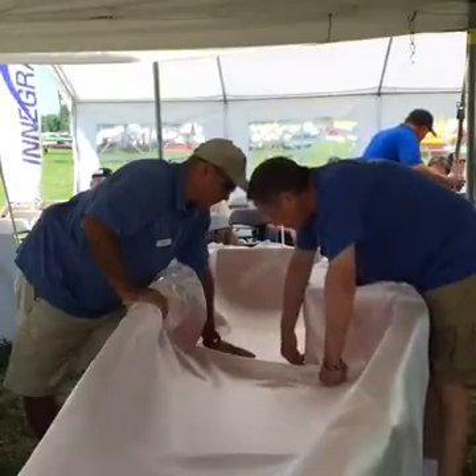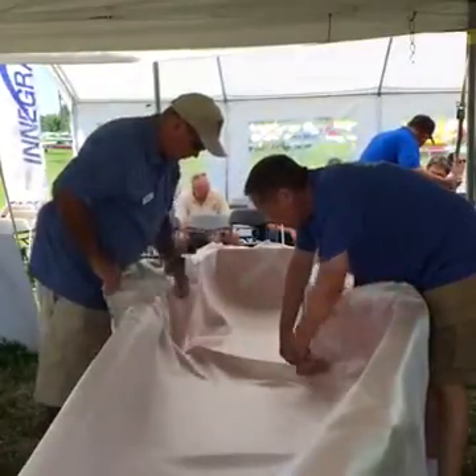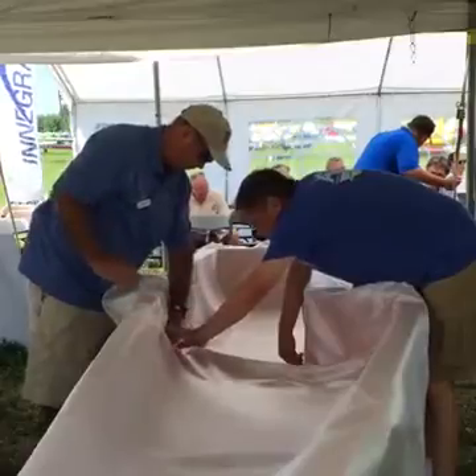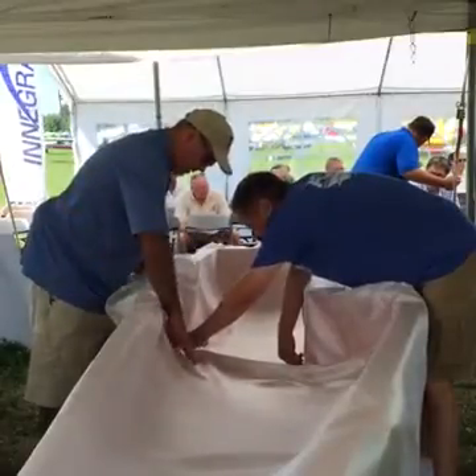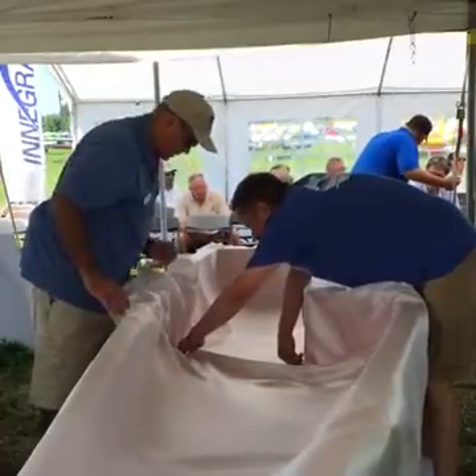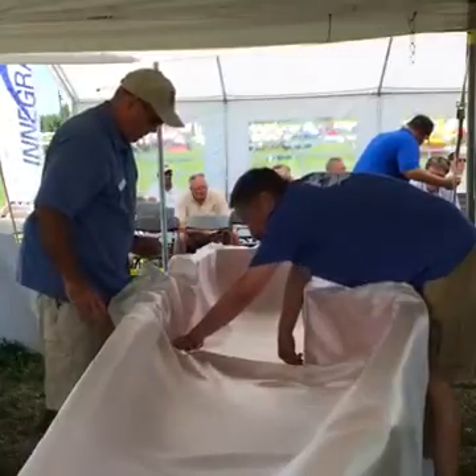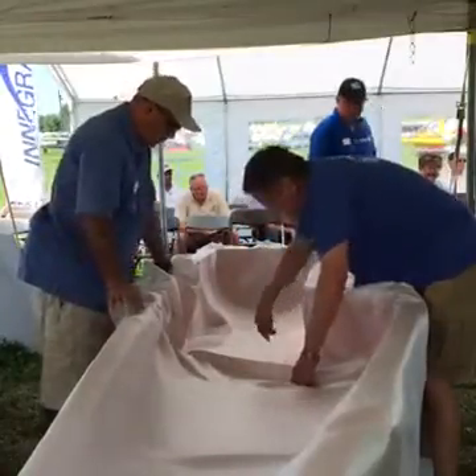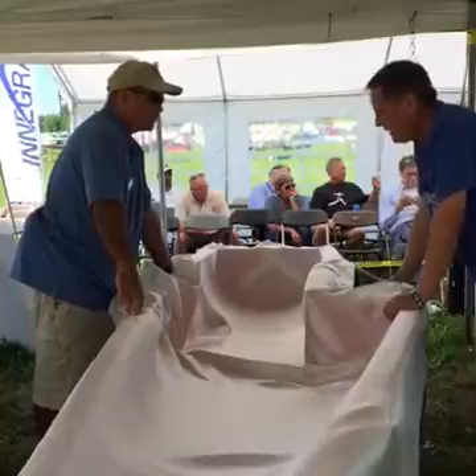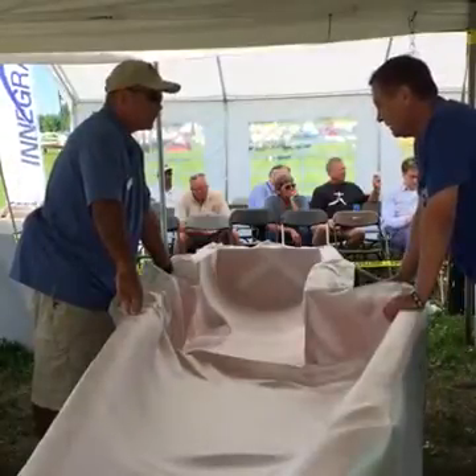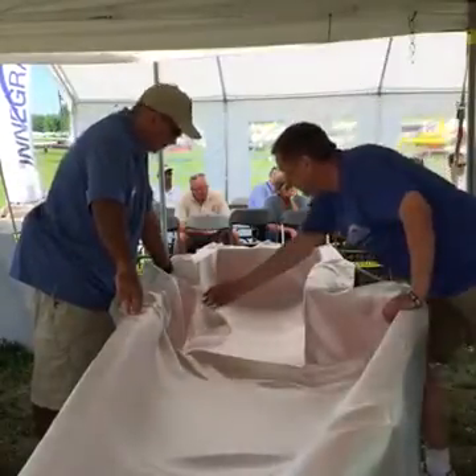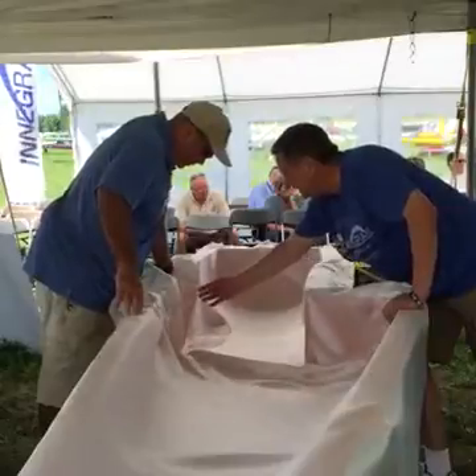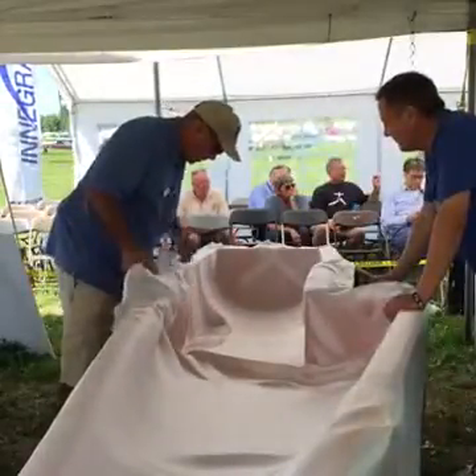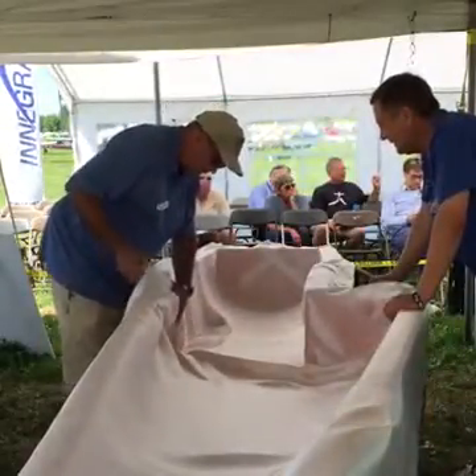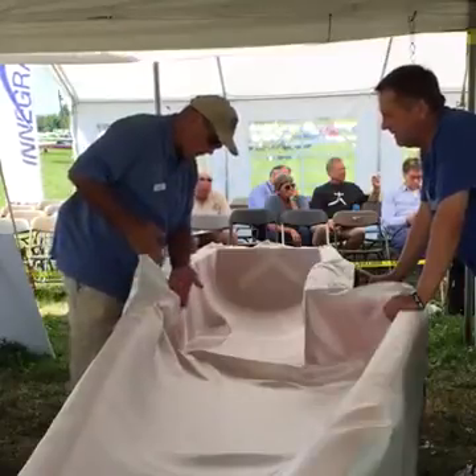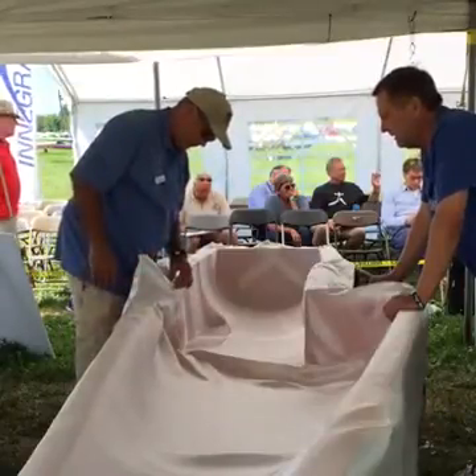So what we have on this part right here behind us is a 3-part system. We have a gel coat, that's the black that you see right here. So what we did was we sprayed black tooling gel coat, and it's a very tough system. So it won't crack, it won't break, it's very tight. Then behind that, we're applying this skin coat behind it. So one layer of basically resin behind it. And that is all done in Composite.